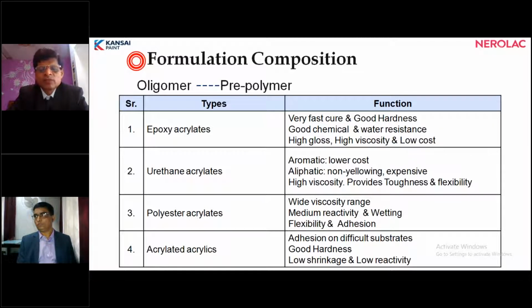Again here mainly two types are there: aromatics, which are of low cost, and aliphatic, that is non-yellowing, which is expensive, but it will provide toughness with flexibility. So a very tough film you can get with urethane acrylates. But again you have to formulate as per requirement because its cost is higher when you use aliphatic. Then polyester acrylates are mainly used for wetting and flexibility. Then acrylated acrylics give good hardness and adhesion on difficult surfaces.